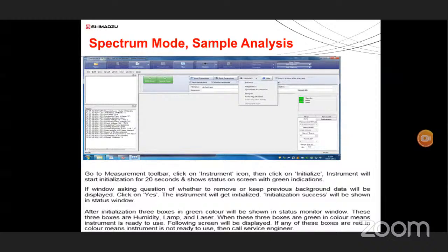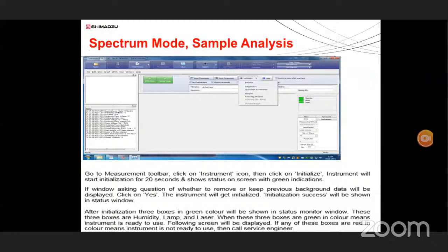If your sample is diluted in any other solvent like acetone, ethanol, or any other material, you have to take the background with that solvent. After the background is complete, we put a minimum quantity of sample on the diamond crystal, just enough to cover it. Don't put excess sample because the crystal part is very small. Then apply torque with the sample holder, so that the whole sample covers the diamond ATR.